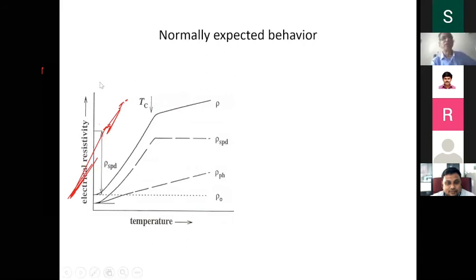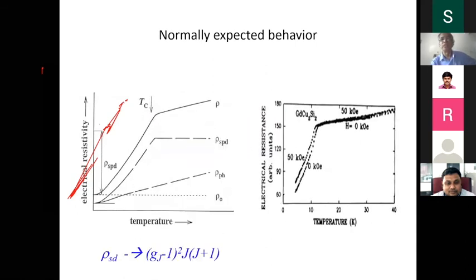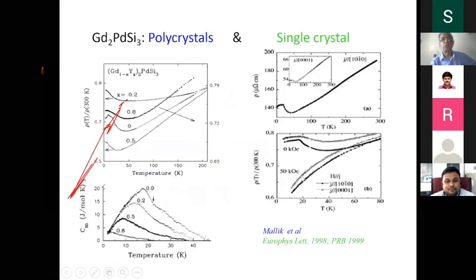Normally, for example, if you look at the plot of electrical resistivity versus temperature, a normal material should show a positive temperature coefficient of resistivity, and then at the magnetic ordering there should be a drop here. Okay, this is a normal material. This is what you should see. I will not go into detail, but for a gadolinium compound with silicon, the experimental data shows a paramagnetic behavior, and there's a drop at the antiferromagnetic transition here. So, for some materials which we reported two decades ago, there is a magnetic ordering here, and there is a minimum here. I already mentioned the minimum as a signature of the Kondo effect, again from delocalized 4f electrons. In this case, it is not coming from delocalization of 4f electrons.